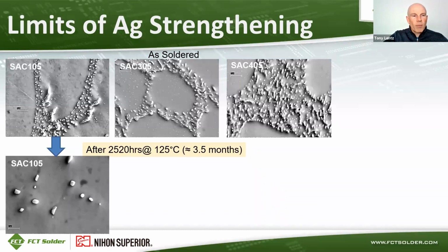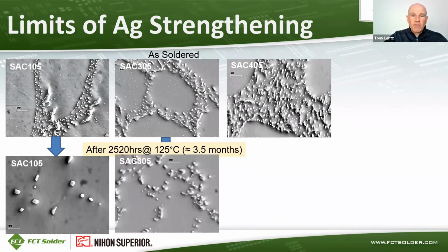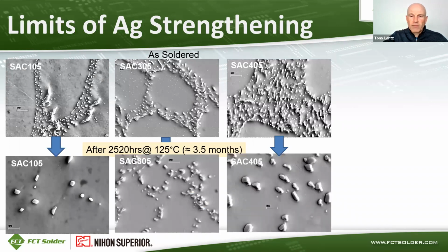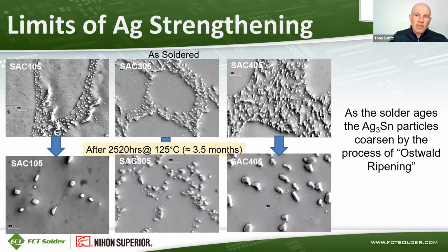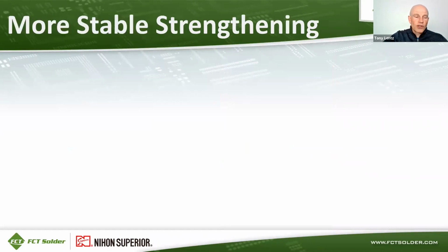The SAC 105 particles coarsened, so they agglomerated together and grew larger in size, and there's much fewer of them. The same thing happened in SAC 305 and SAC 405. So as the solder ages, the Ag3Sn particles coarsen through Ostwald ripening. They also lose their effectiveness as they coarsen. So to get a more stable strengthening effect, we need to look at elements besides silver for the strengthening effect.